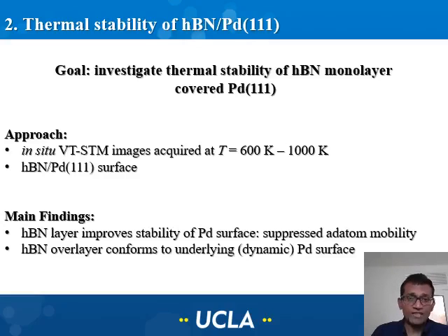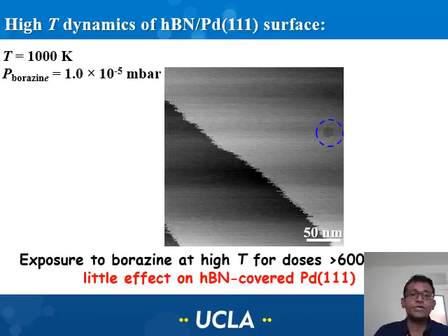And the main finding, interestingly, is that compared to bare palladium, hexagonal boron nitride covered palladium is thermally more stable. From our studies, we find that the stability is increased because the atom mobilities on palladium wrapped under hexagonal boron nitride are significantly suppressed. And without further ado, let me show you what we actually did.